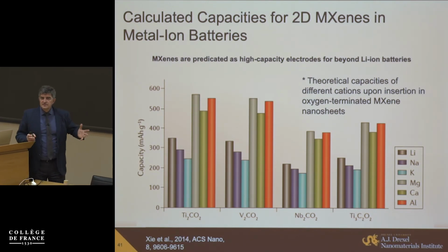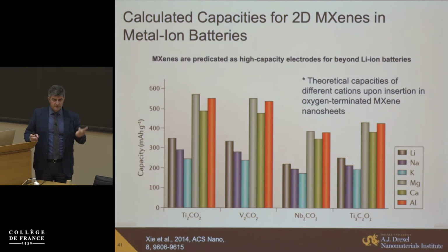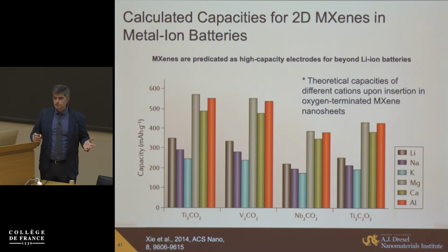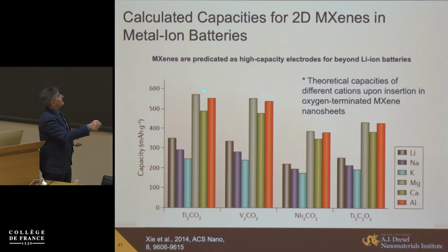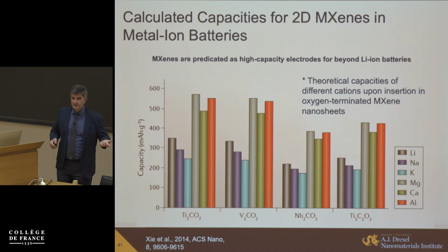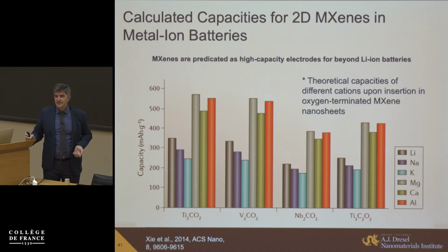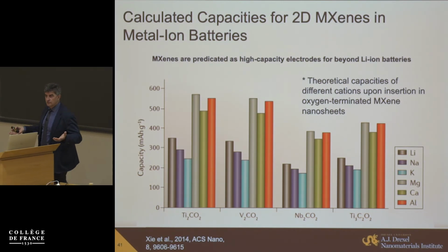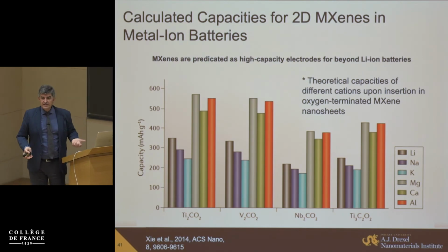What is important now? We know we have this very large family of materials with tunable structure and tunable properties: conductivity, redoxability, transition metal, number of layers, ability to confine and intercalate ions. What is important is that we need to find where they can really do work and where they can be useful. One straightforward approach is, okay, let's take these materials and intercalate lithium and get the best lithium ion battery ever. But DFT calculations predict that on the best day, in the best MXene, like titanium 2 CO2, you can get something like 400 or 500 milliamp hours per gram, theoretically. Well, you cannot compete with silicon in this case, let alone metal anodes. So again, you can do it, but you're not going to get anything extraordinary.